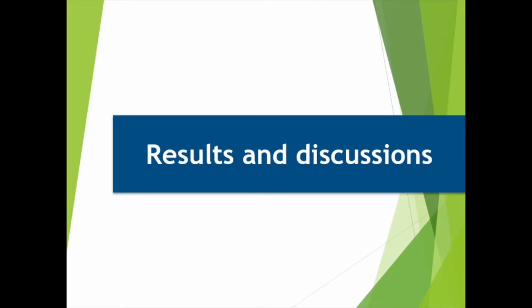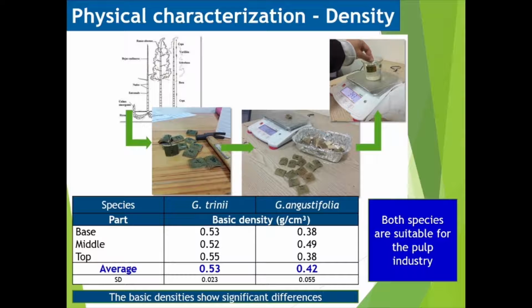Now we will see the main results obtained. The basic density was determined for 36 square pieces of 25 millimeters on each side from three different parts of the stem: base, middle, and top, which were saturated with water for 36 hours, and the volume of the samples was determined by the Archimedes method. Then it was brought to the oven until constant weight or dry weight. The table shows the basic density of each species, which present significant statistical difference between the different parts of a stem. It was determined that the basic density range of both species were suitable for the pulp industry.